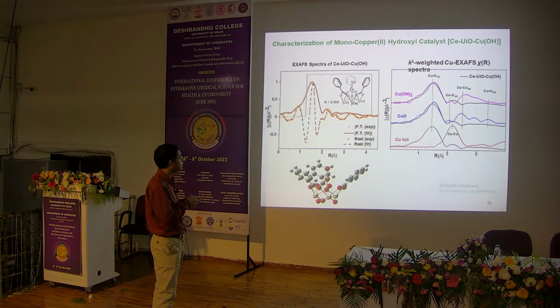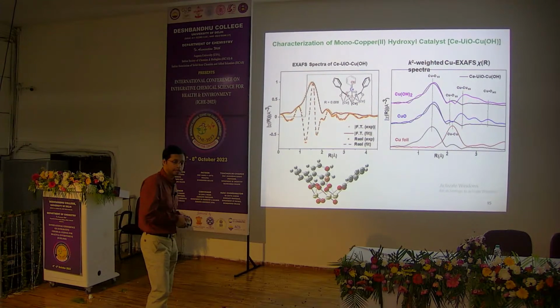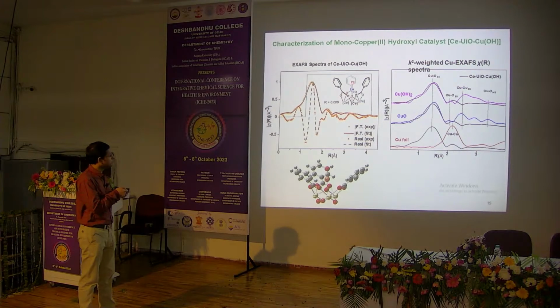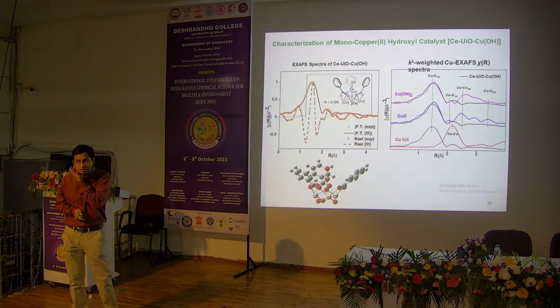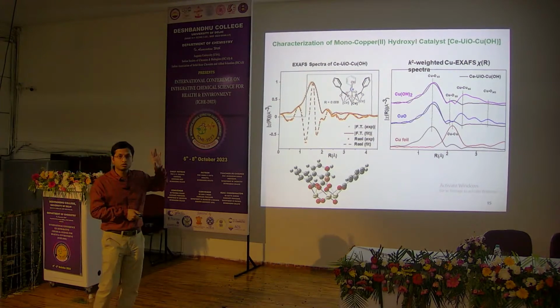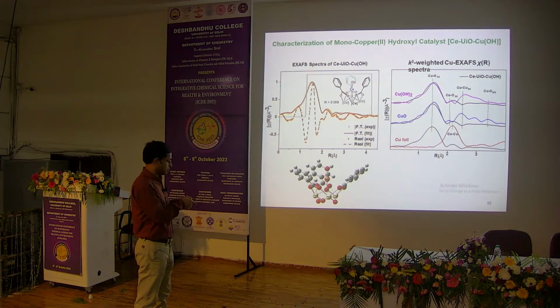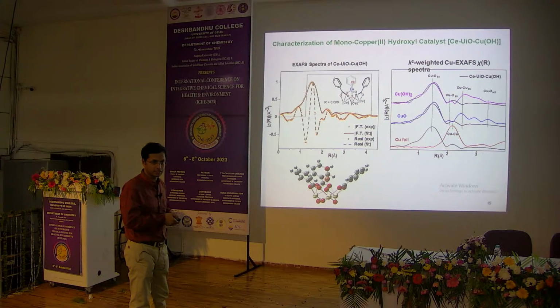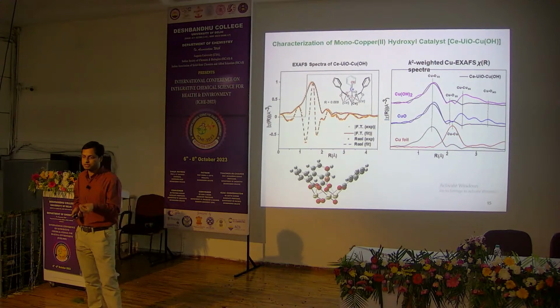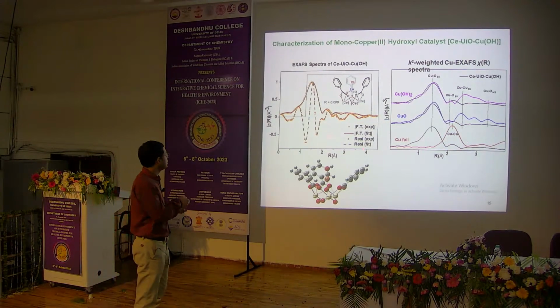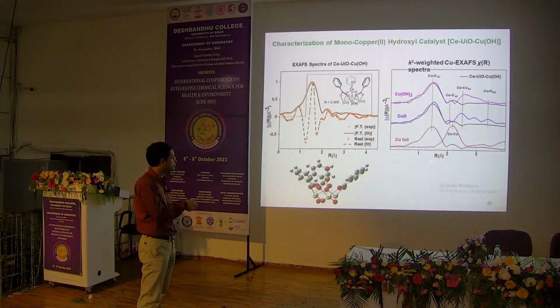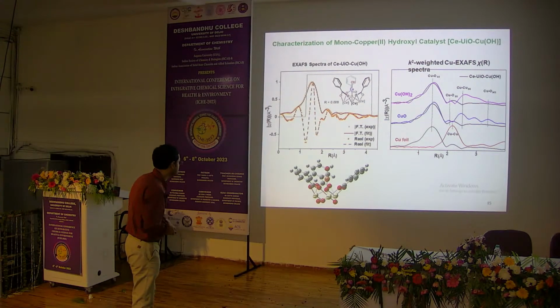If you compare with the other copper standards like copper dihydroxide or cupric oxide, there is no copper scattering. So that indicates that the species we have is a monomeric isolated copper hydroxyl species, and there are no neighboring coppers. There is no copper nanoparticle. We also compared the EXAFS with the copper foil, metallic copper foil, and fitted it with 2%, 1%, 5% copper nanoparticles, and we found in this MOF catalyst there is no metallic copper present.